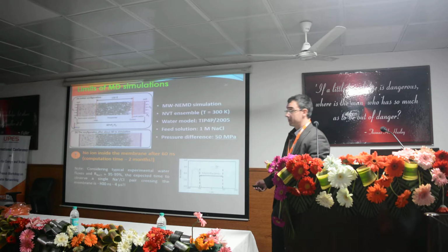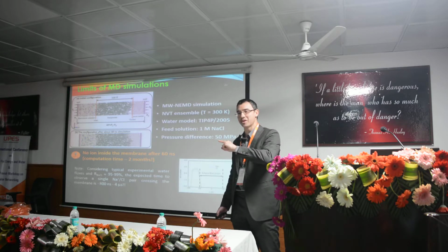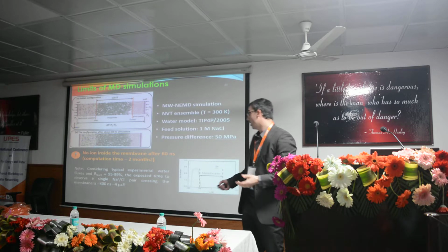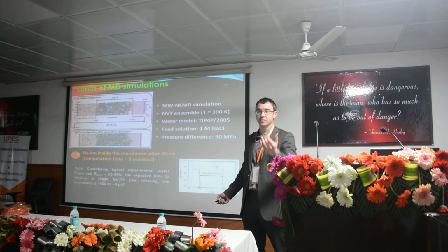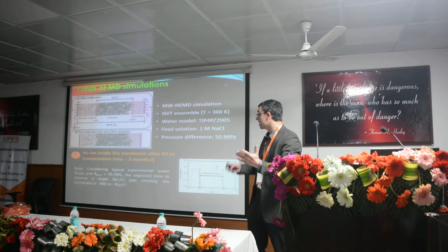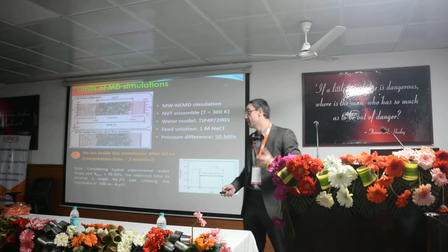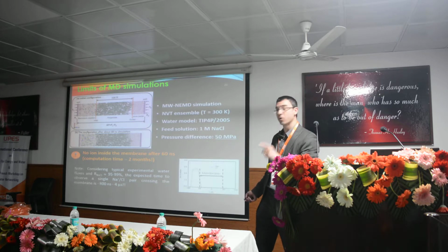Okay? Well, you can easily understand that you have a problem if you are interested in investigating ion transport through polymer membranes with these tools, because ions don't enter into the membrane. If you consider typical experimental fluxes, water flux through this kind of system, and rejection rates, say, between 95 and 99%, based on the literature, then you can estimate that the time required to see a single pair of ions crossing the membrane should be between 800 nanoseconds and 4 microseconds.